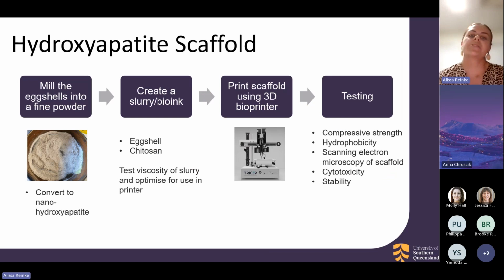So in order to actually create the scaffold itself, I needed to obviously get a lot of eggshells, and I milled those into a fine powder. I found less than 100 micron is working well, and some of that was converted to nanohydroxyapatite. From there, I had to create the ink that can be used in the printer. So I combined eggshell and chitosan with a binder, and then had to test the viscosity of that to make sure it would be usable in the 3D printer. The printer then obviously printed the scaffold, and then further testing is currently being completed.